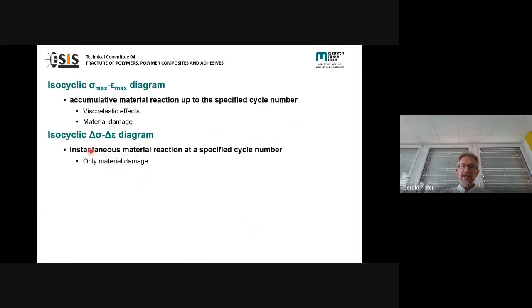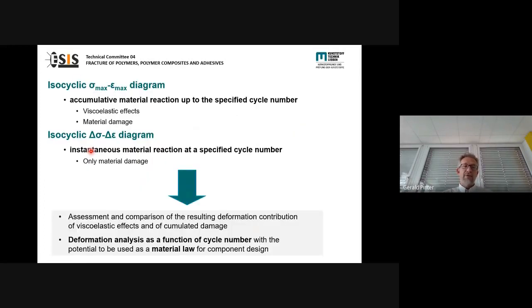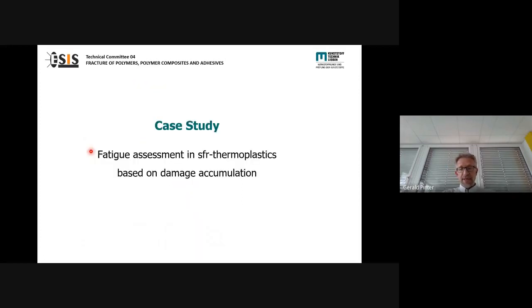And by comparing again these 2 procedures, we really get an idea whether the polymer is more sensitive to viscoelasticity or more sensitive to material damage. And the big advantage of this isocyclic stress strain diagram is that we really have a stress strain relationship that can also be used as a material law in the end for simulation procedures. So that was very quickly, really very quickly, a short introduction into conventional stress-based fatigue in polymers.